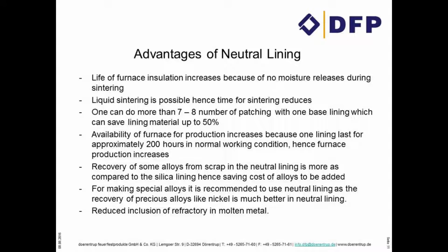Recovery, okay, then another major advantage of this neutral lining is the recovery of ferroalloys. In silica lining with steel castings or some of these special alloys, the recovery of alloys is less, which we have practically observed, whereas in the neutral lining you can get much better recovery for manganese and others. In some steel castings it is very difficult to make them in silica lining, whereas in neutral you can make any special or difficult castings having high alloys like moly and nickel. These castings you can make in the neutral lining without any problem.